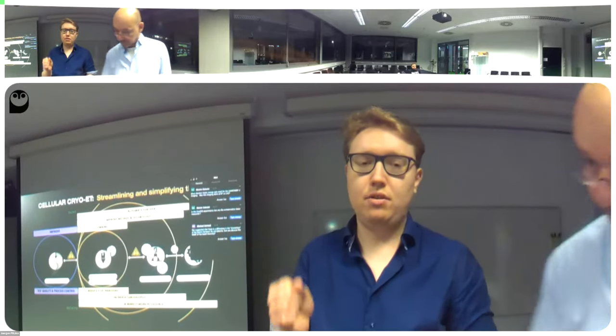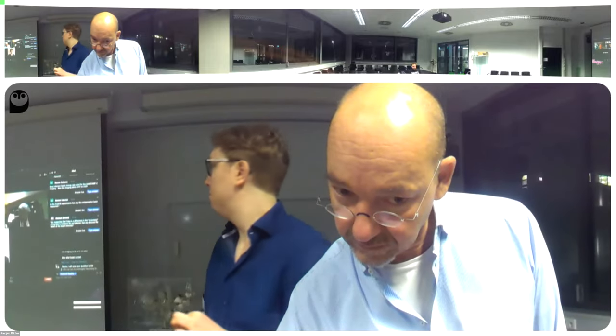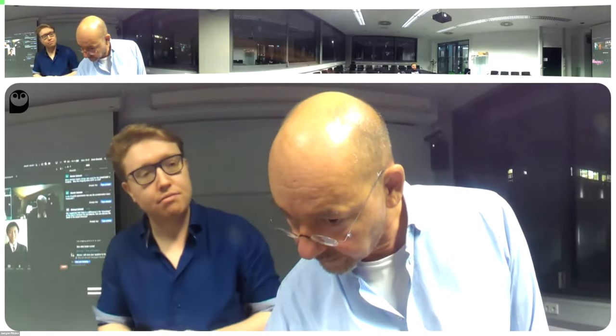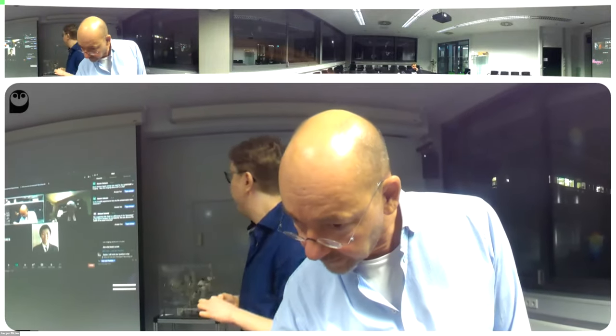For the plasma source, it's different because you have an aperture where the ions are shooting out of the plasma chamber, and you get a virtual source size of around 10-ish microns. And therefore, at the lower currents, you have a very non-sharp beam, meaning that even your images become very blurry, and the depth of focus gets worse. Whereas at high currents, you can actually still, with for example xenon or argon, get a very nicely focused beam and therefore also remove material in a more focused manner. So I hope that answers the question. Thank you.